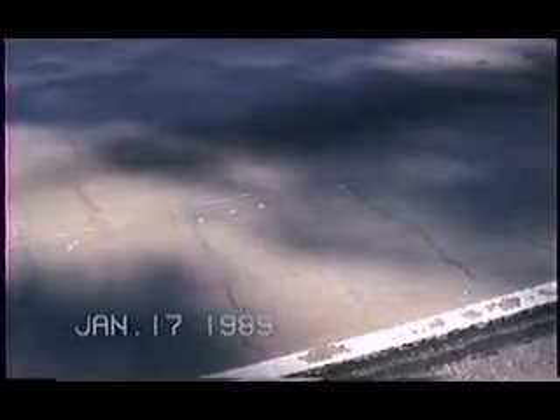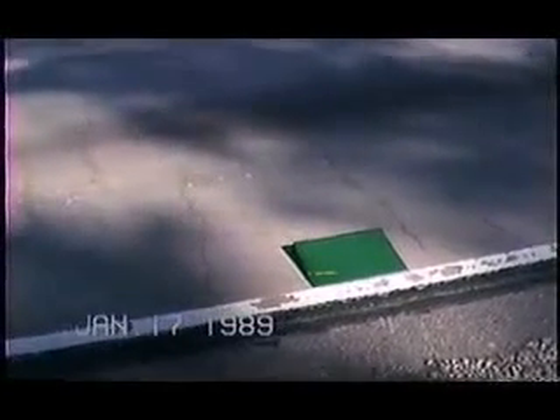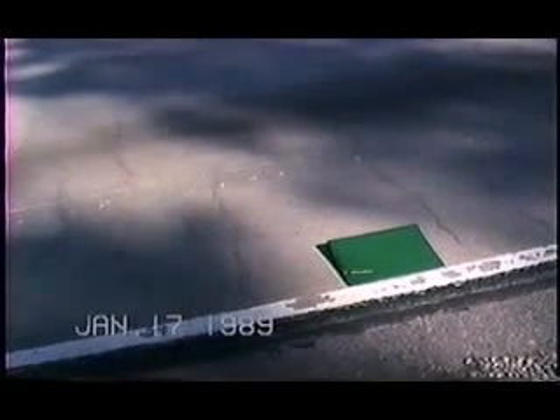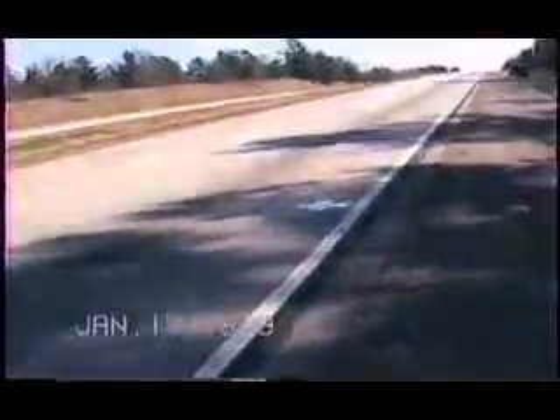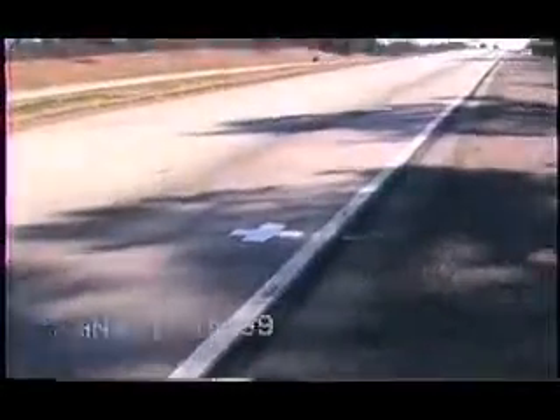Okay, here's another set. We're in the shade right here, so it may be difficult to tell some of this. You see the cracks are quite closely spaced right in here. To try to give some scale and perspective to this, see those cracks on either side of it that go all the way over to the edge of the lane are approximately 2 feet apart, slightly more than 2 feet spaced. And many of the other cracks, though, which appear to be in the development stage, are somewhat closer spaced than that, including one right up over there, which are 2 cracks which appear to be around 5 to 6 inches apart.